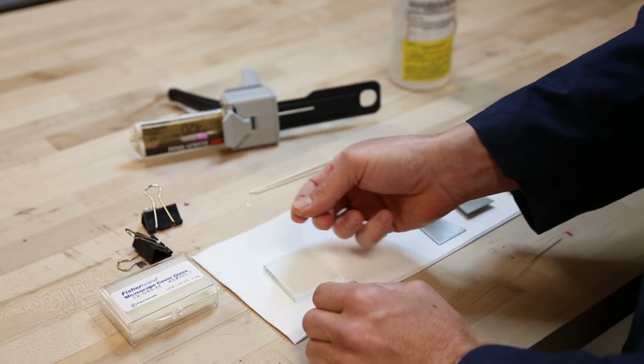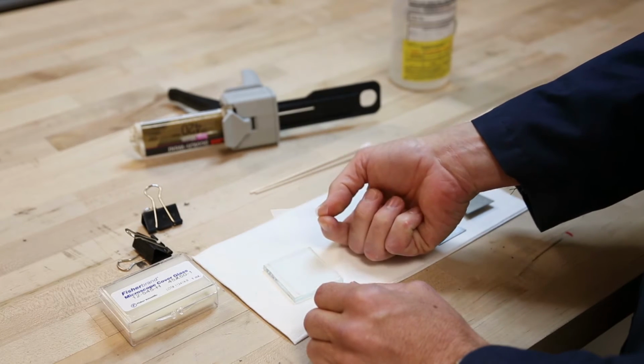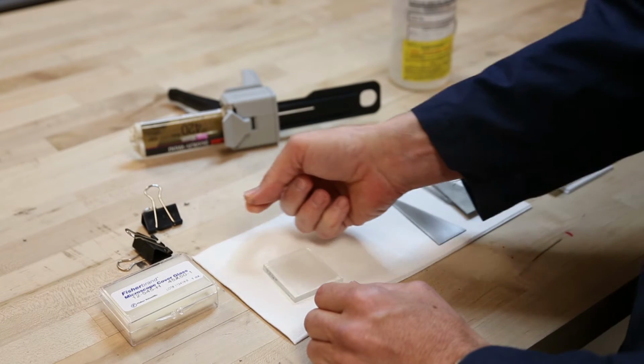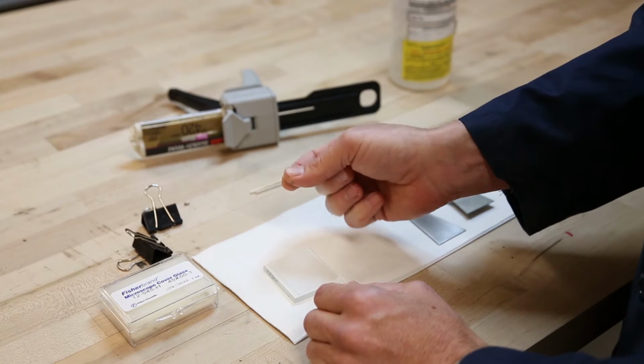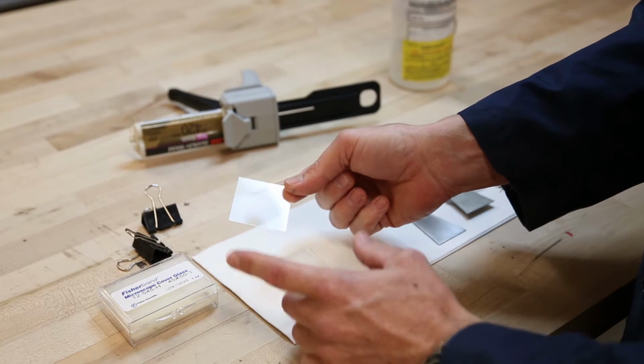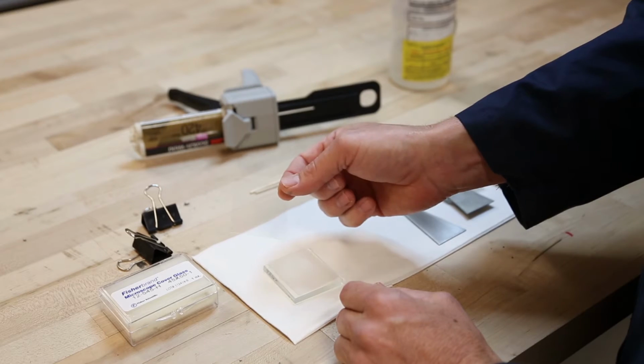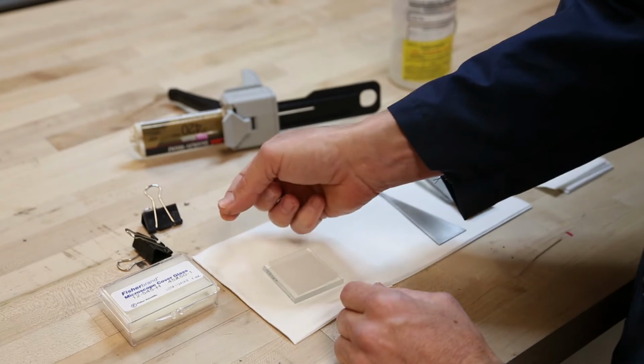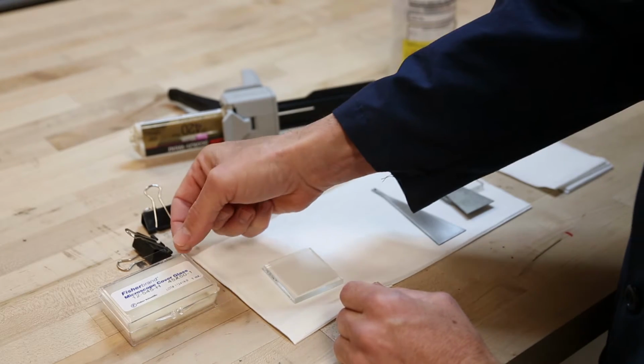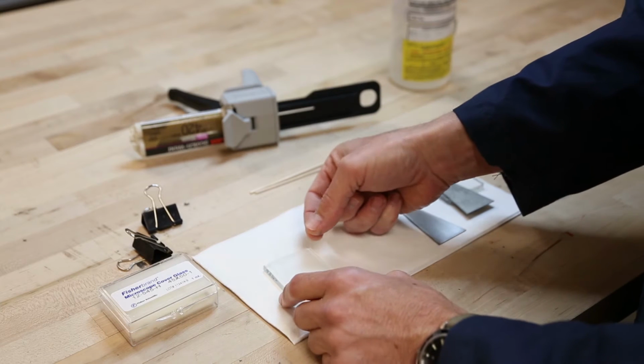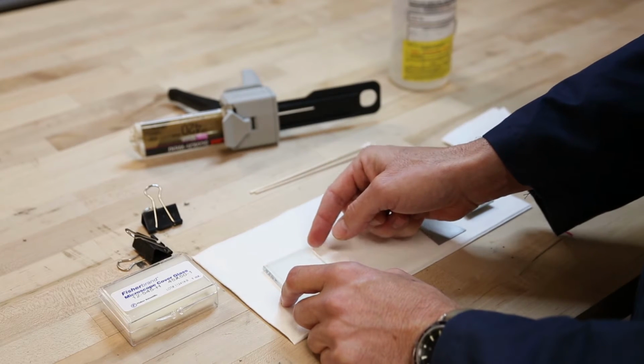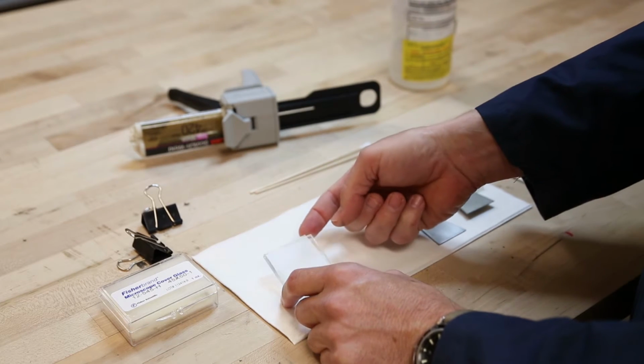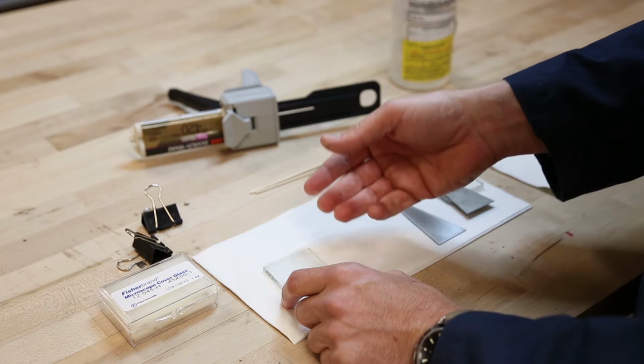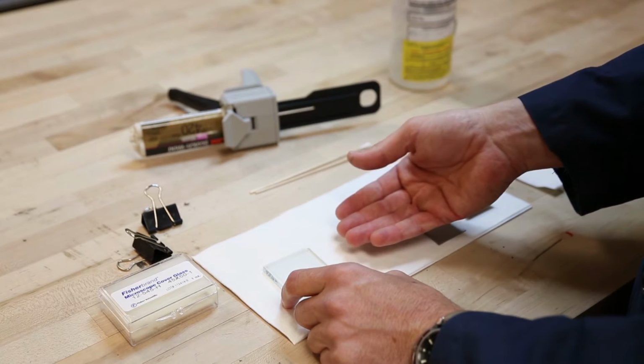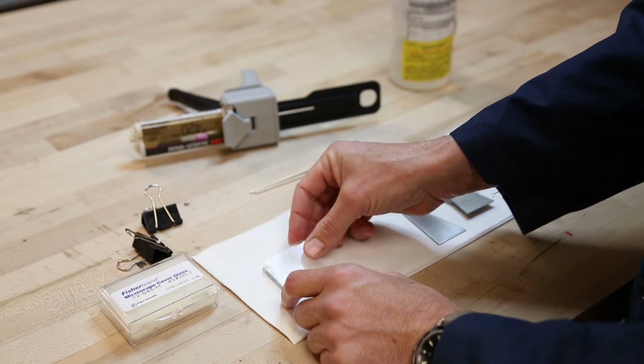slide. This is a Fisher product. It's roughly 150 microns thick, and it's 45 by 50 millimeters on a side. Ideally, I'd like a little something bigger, but this is an off-the-shelf product that's easy to order. The reason why I'm laminating the thin microscope slide to the thick slide of glass is so I'll always have a glass encapsulant interface to test.